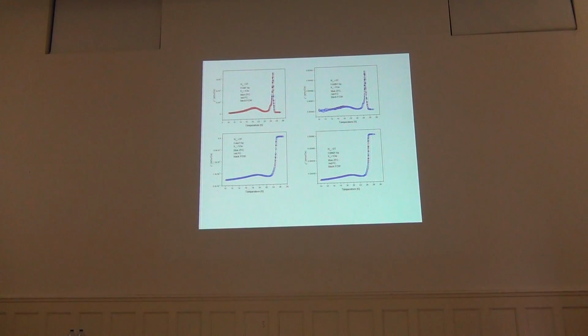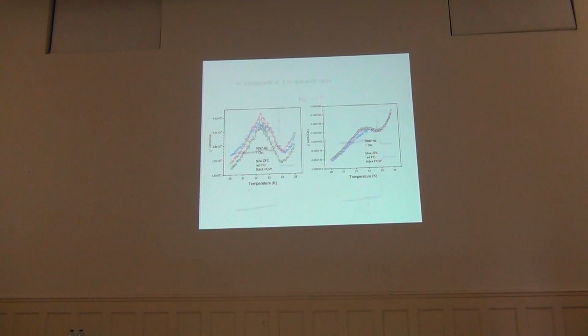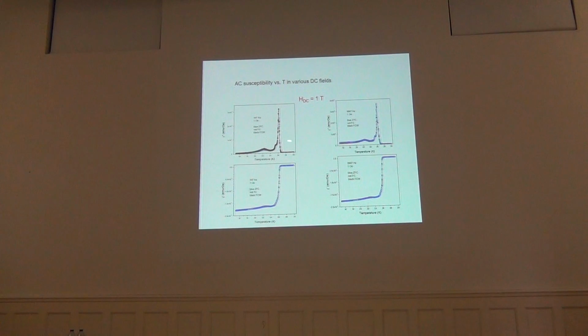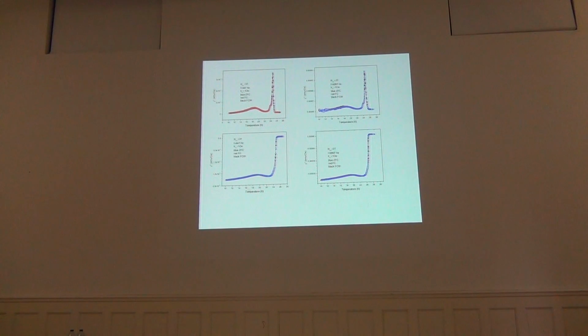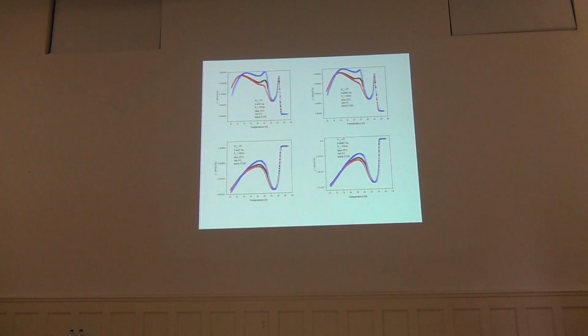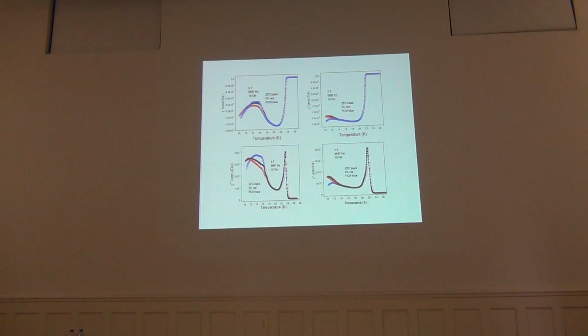We repeated this also at other fields. Now the difference between this one and the previous one is that most likely with this low field amplitude, the vortex is mainly in the Campbell state, in which it oscillates just inside the potential well of the pinning center, while when we put 10 Oersted, so a much higher excitation, it can go out of the pinning well. So this happens also at 3 Tesla, 5 Tesla. Okay, so this is 3 Tesla, 5 Tesla, and in 7 Tesla it starts to fade off the effect, but we are now probably going towards a wipeout of this anomaly.